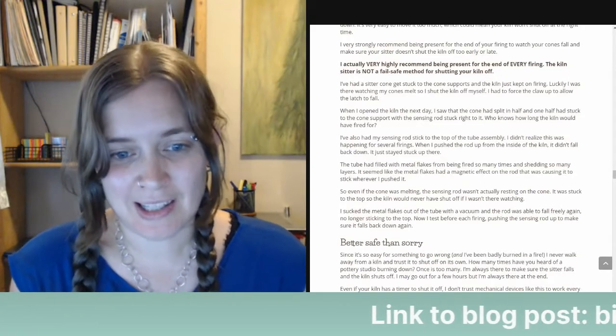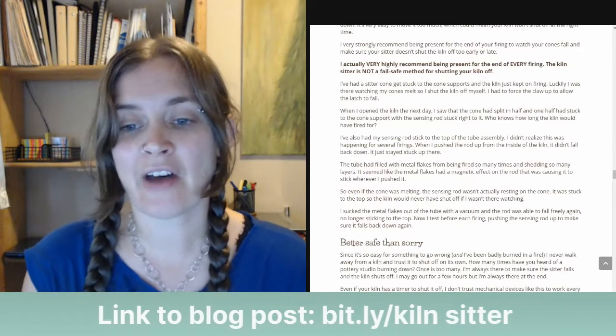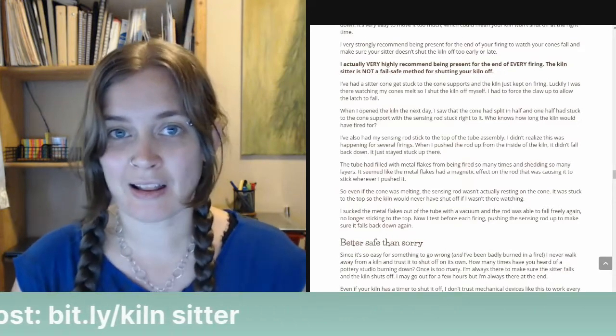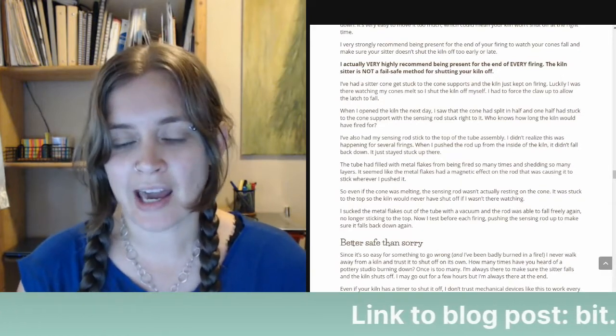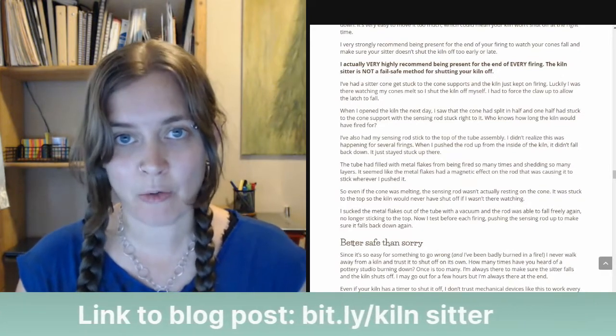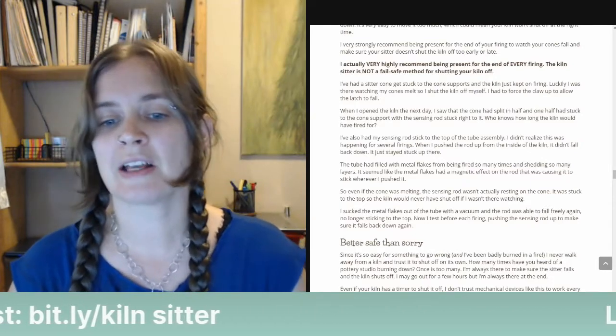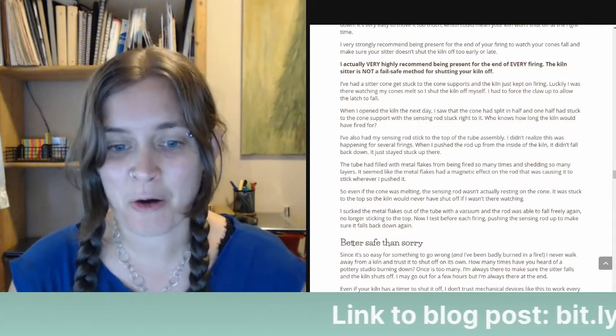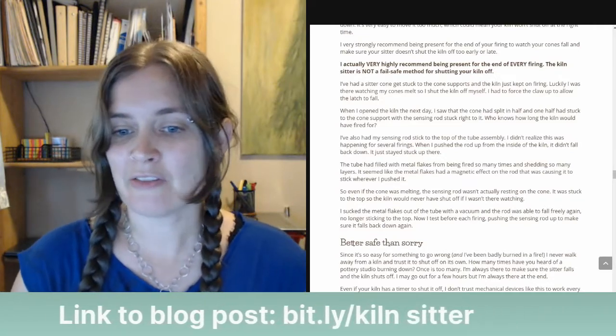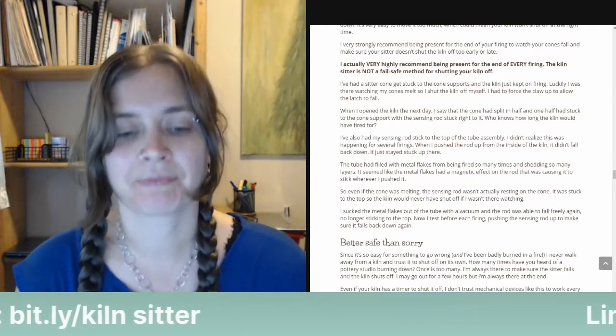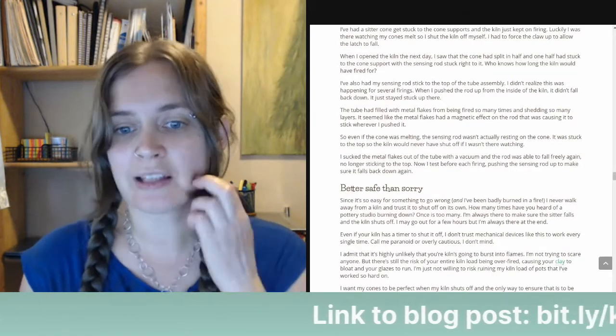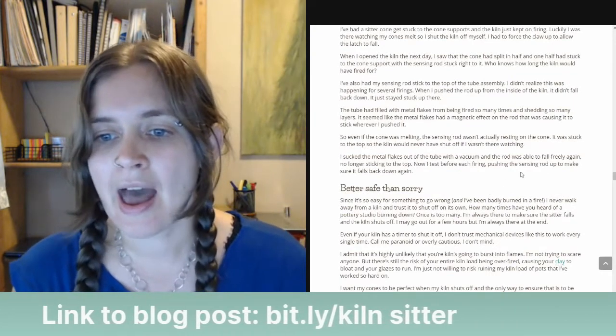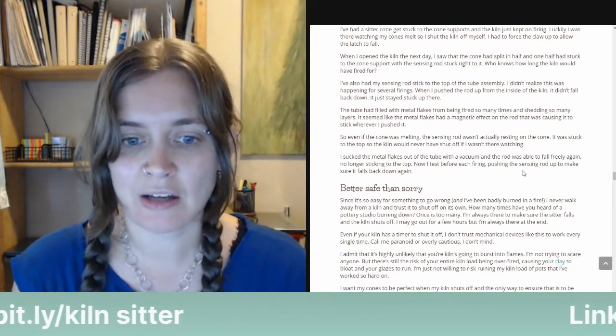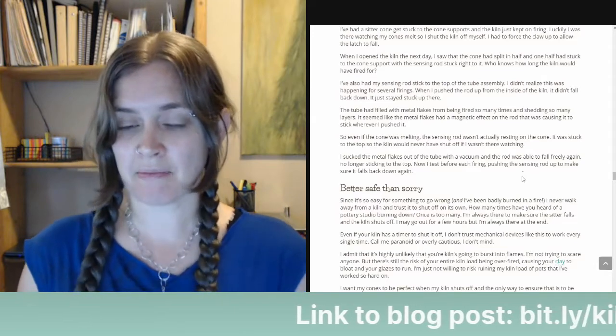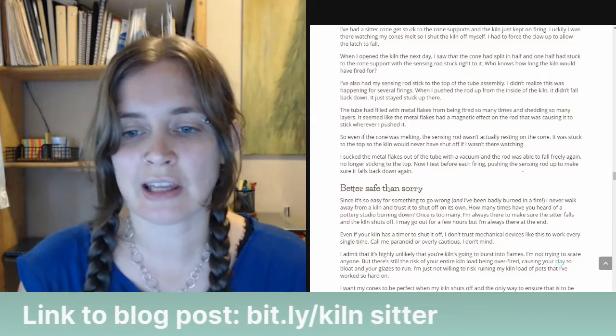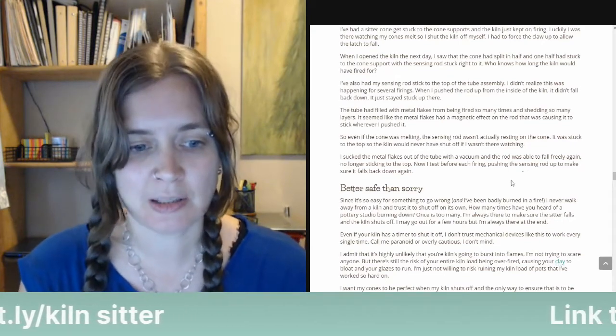What I discovered was the tube had filled with metal flakes from being fired so many times and shedding away so many layers of oxidation. It seemed like the metal flakes had a magnetic effect on the rod that was causing it to stick wherever I pushed it. So even if the cone was melting, the sensing rod wasn't actually resting on the cone. It was stuck to the top, so the kiln never would have shut off if I wasn't there watching it. I ended up sucking out the metal flakes from the tube assembly with a vacuum, and then the rod was able to fall freely again, no longer sticking to the top. So now I test my sensing rod, make sure it moves up and down freely before every firing, just to make sure.